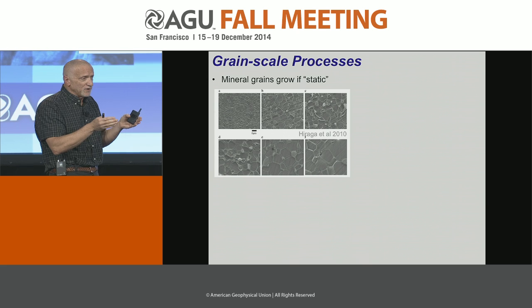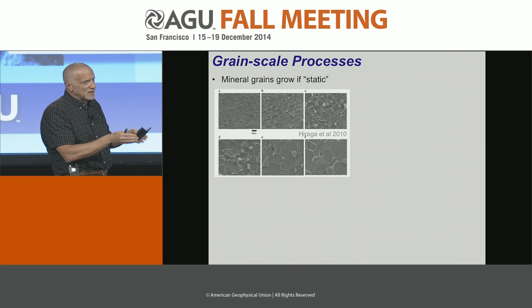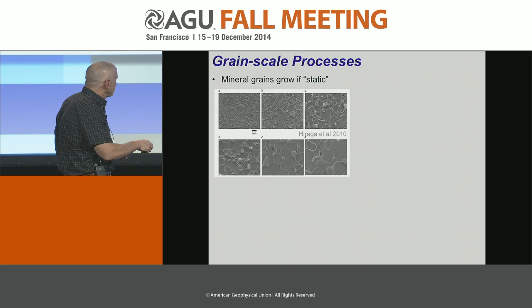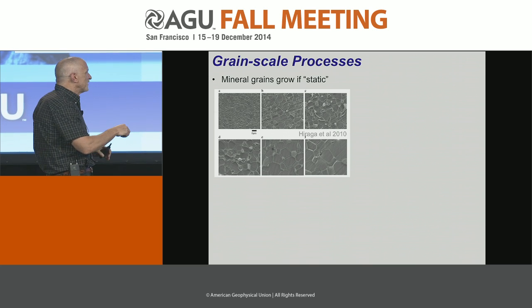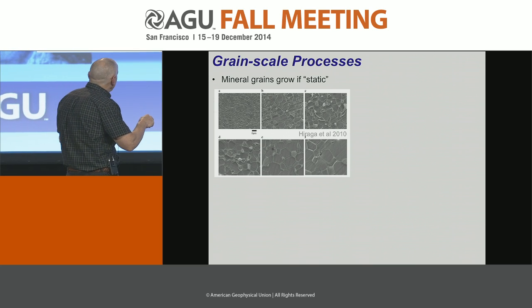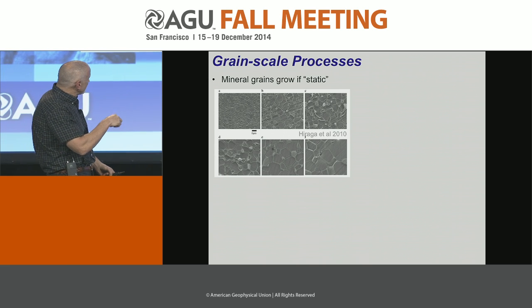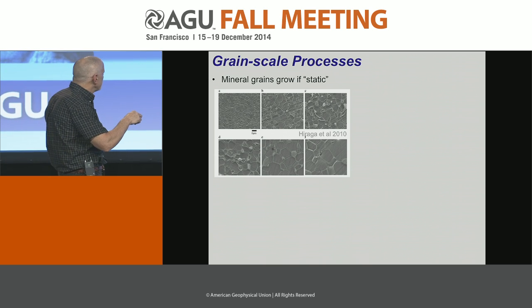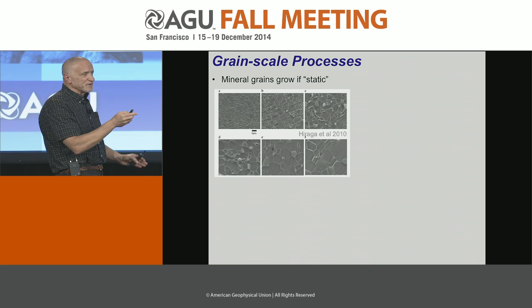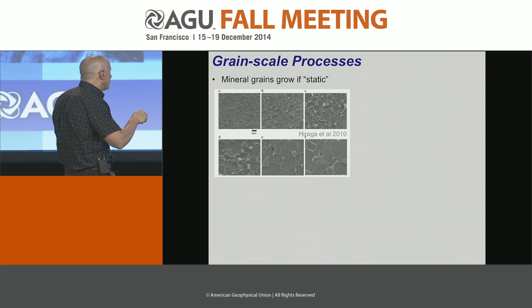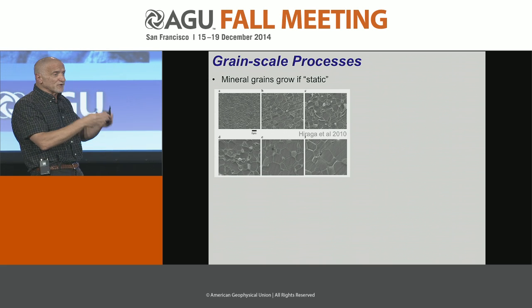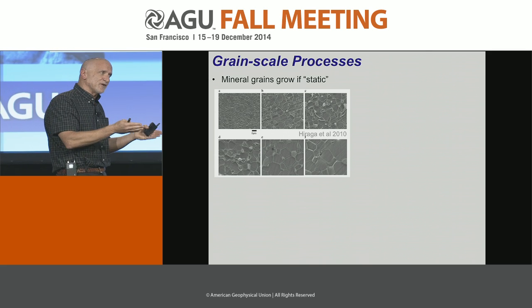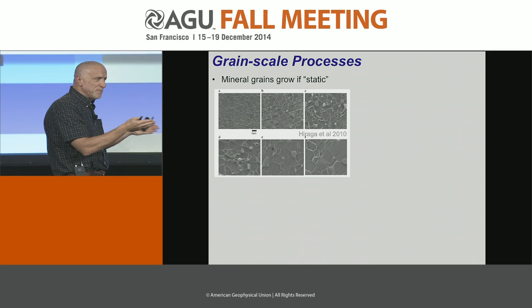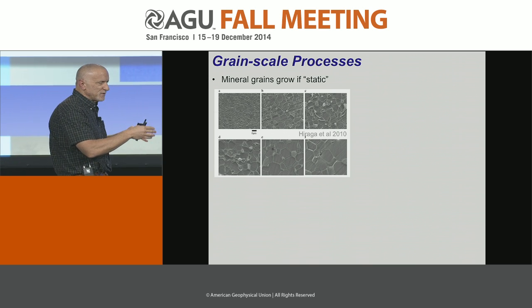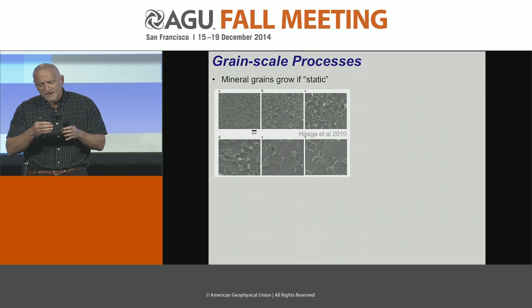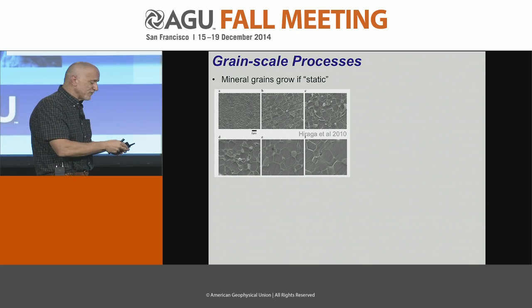In fact, if I take a rock with grains in it and let it sit there, not at room temperature, but at some higher temperature, something more characteristic of the mid-lithosphere, 900 degrees or so, the grains will eventually grow. In a laboratory experiment, very nice ones done by Hiraga's group in Japan, these grains will grow over about 50 hours, 2 days, and you'll see this grain growth occur. They start with very small grains, but you can actually see it occur. As the grains grow, this material would ostensibly get stiffer because the grains are bigger. It's harder for it to creep, at least certainly by diffusion creep, because as grains are bigger, diffusion creep is less efficient. It would become stronger as the grains grow.